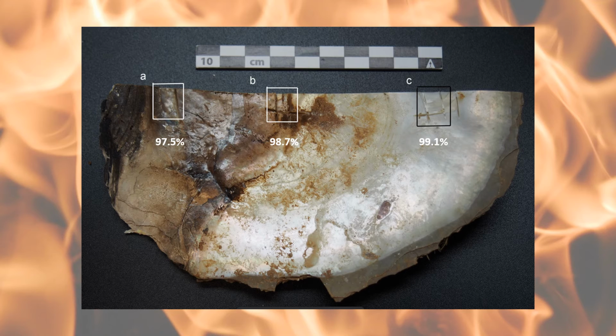Now, the temperature measured in the fire that this was sitting in was over 600 degrees, which is over what any textbook would say recrystallization should happen. And yet, even in the most burnt portions, we've got aragonite at 97.5% of the total mineral content. So that really raised a lot of questions, and it was results like this that prompted more formalised studies that took place over the ensuing years.